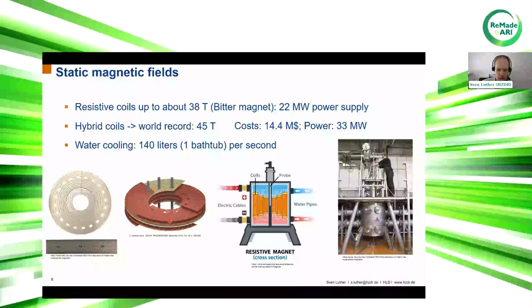And these plates are arranged in a helical format, where in between you have some insulating layers. And you can see this is the cross-section of such a resistive magnet. So you have the electrical power supply to run the magnet to create these high magnetic fields, and then you have the water supply to cool down this magnet. So we have cool water below 10 degrees Celsius going inside the magnet, and outside of the magnet, we have water at 40 degrees Celsius. And this is how such a magnet would look inside the lab. Here you have this big tank where the magnet sits inside, and the water is running through the magnet to cool it down. Then on top we have the cryostat and people inserting the probe inside the magnet.